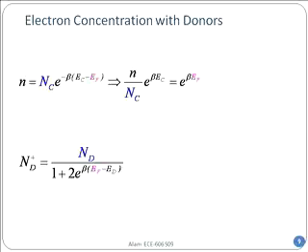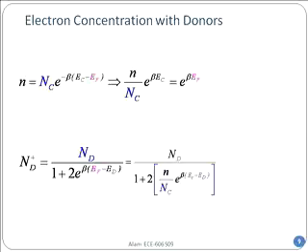But you see, I also have, in the magenta, I have shown an EF, but from the top expression, I could replace that. All I did, you see, from the top expression, the magenta EF, I have replaced it in the bottom one. Now look at this expression carefully. What is unknown in here? The EC is known, right? Conduction band. E sub D is a donor level, known. NC, effective density of states in silicon, I know that. So in fact, if you look at it, except for N, that's actually a constant. I mean, I know ahead of time for the material.